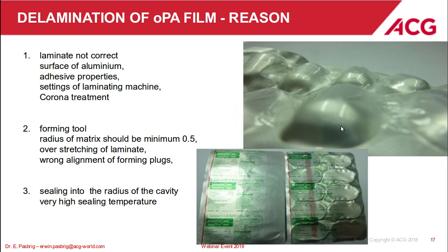Then for sure, setting of the laminating machine. If the drying of the lacquer, the adhesive, is done too high, so the material surface temperature is very high, one part of the adhesive will evaporate. And for sure, if the OPA film is not corona treated, then delamination will happen earlier as well. But the laminate is not the only cause for delamination. The forming tool has an influence as well.